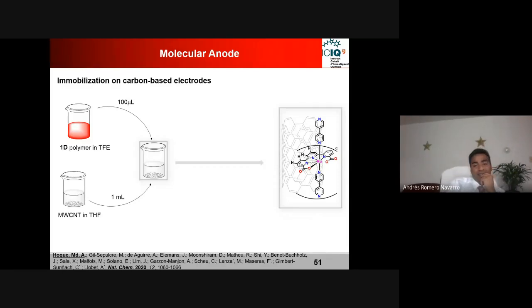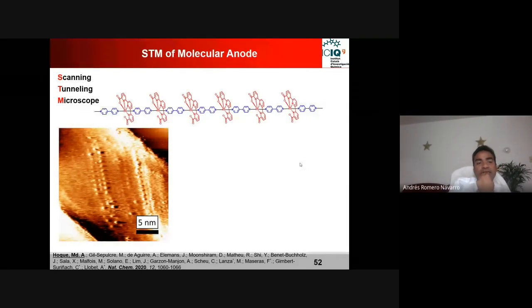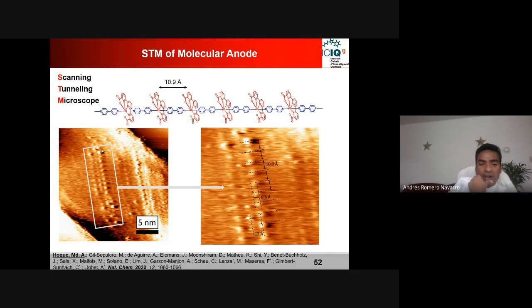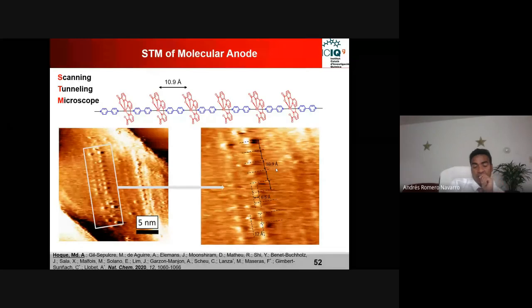So we thought, okay, we did it, but whether we did or not, we wanted to characterize that material, right? So then we did this STM, the scanning tunneling microscope. It is a very advanced technique to see molecules at the molecular level by microscope. So we thought we have this polymer. Here I'm showing this part is the zoomed portion. You can see that there are bright bulbs, right? These bright bulbs correspond to 1 ruthenium unit molecule. And the distance between these two bulbs is, let's say, 10.9 angstrom, which has been measured from this microscopy.